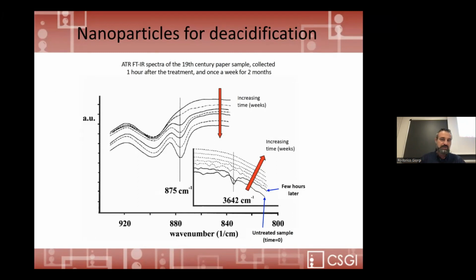In this case, you can see some infrared spectra, where you can see that with time, in a few weeks, we have a significant increase of calcium carbonate signal, 875 wave number. And you can see that just after a few hours or a couple of days, no more than a couple of days, the signal coming from hydroxide completely disappears. So fast neutralization reaction and very quick transformation of hydroxide to carbonate.